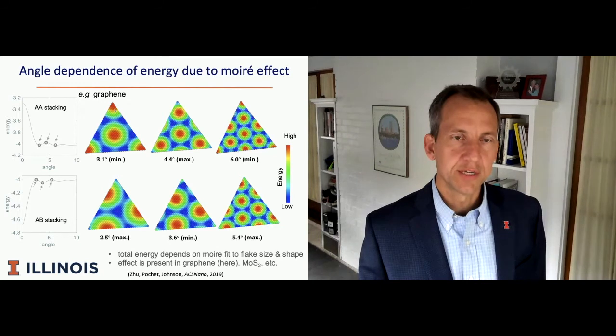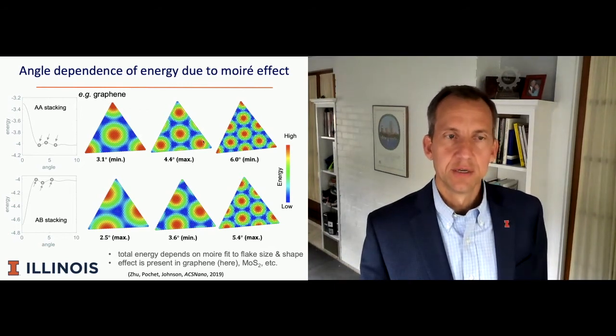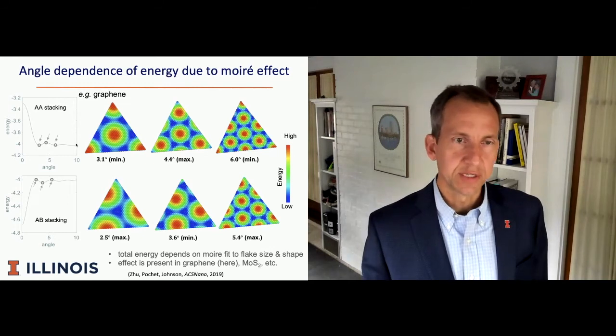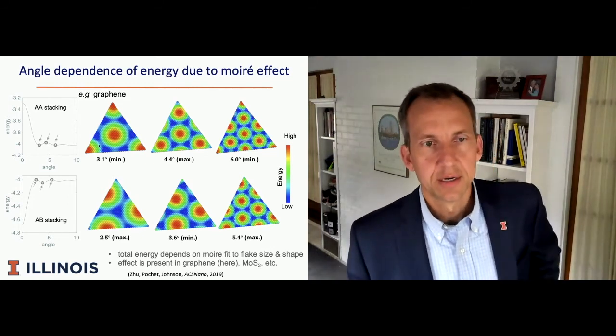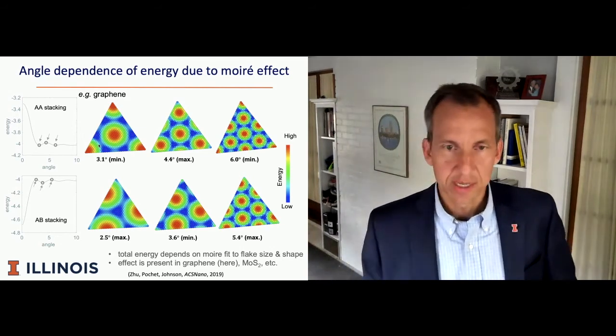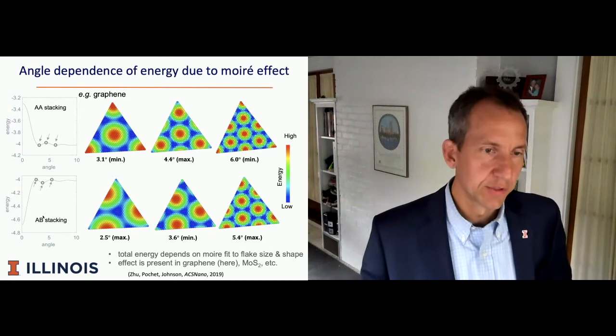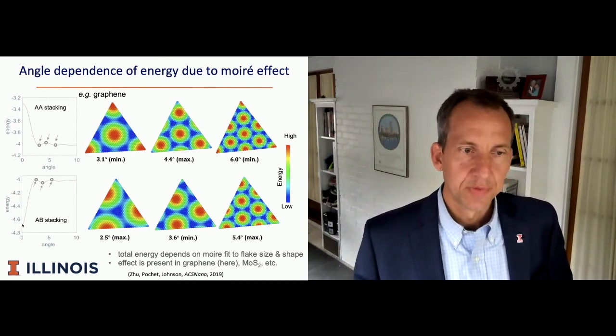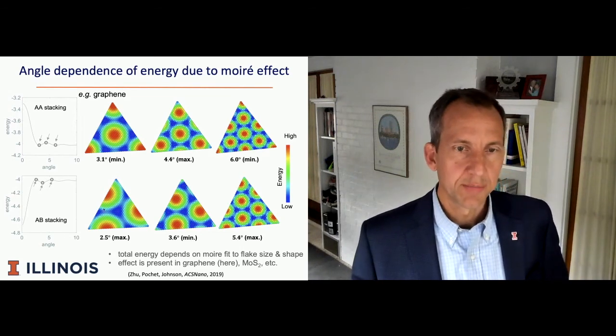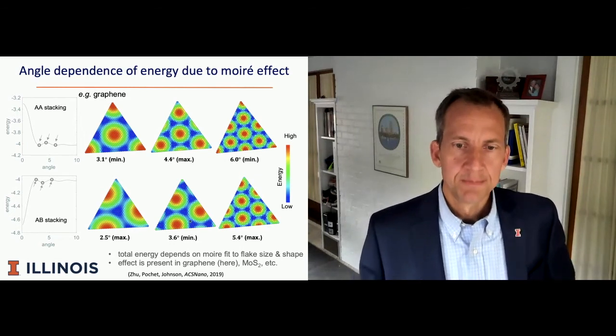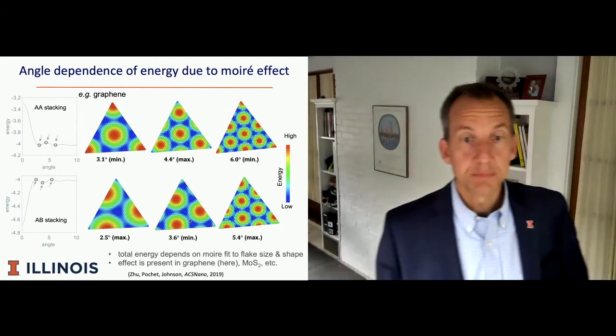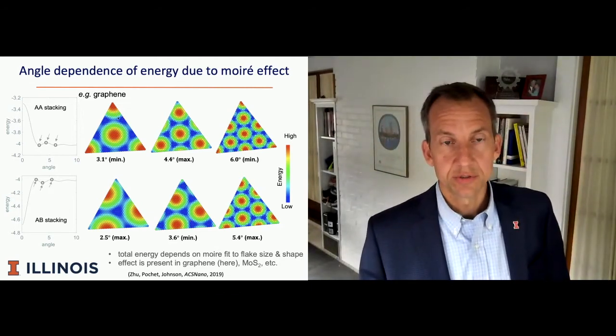And at the 3.1 degree rotation, this is what the moire pattern looks like. If we go a little bit further to 4.4 degrees, we see a different moire pattern, and we see a local maximum in energy. And we can continue and see another local minimum, and we can proceed along and see higher and higher orders of minima and maxima at discrete angles as we go. AB stacking looks similar, except the 0 degree case is the global minimum energy. The first maximum occurs when the moire pattern looks like this. Second minimum occurs when the moire pattern looks like this at 3.6 degrees. And so we find that the total energy depends on the fit of the moire structure to the triangle.